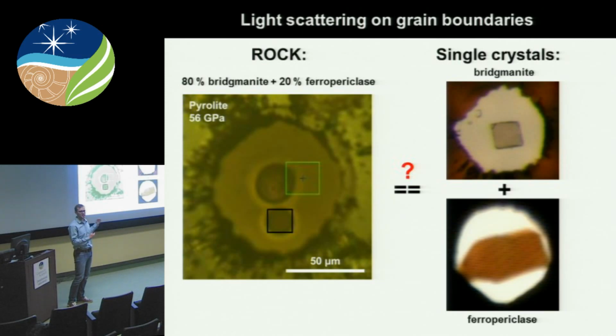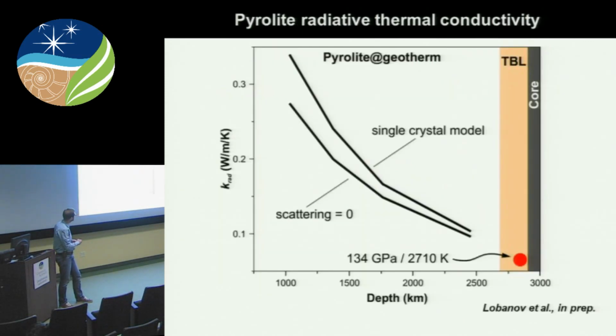However, we can ask a question whether the optical absorption of pyrolite can be explained simply by combining absorption spectra of single crystals, where you would expect the scattering to be minimal. So if you do that, actually, you can come up with some sort of a scattering correction. And here is what I call the single crystal model of radiative thermal conductivity. And again, to my big surprise, the difference between the zero scattering and the single crystal model is relatively small, probably within the experimental uncertainty anyway.